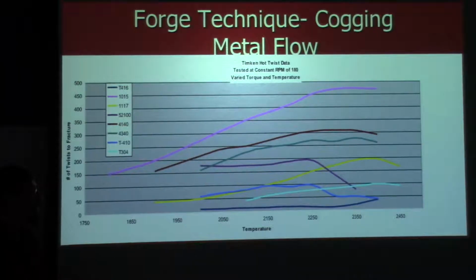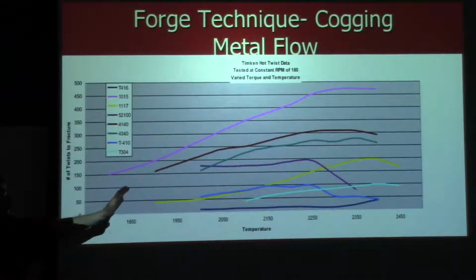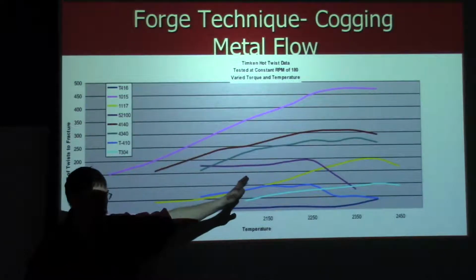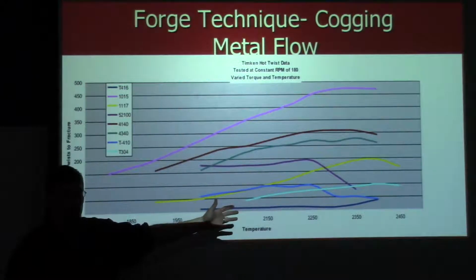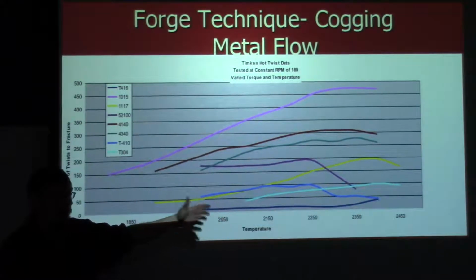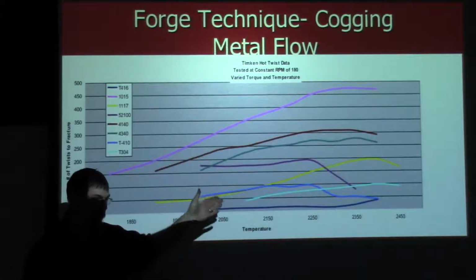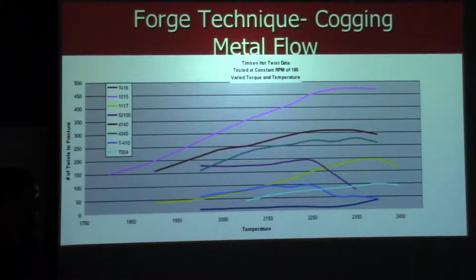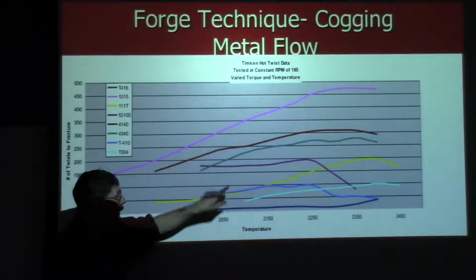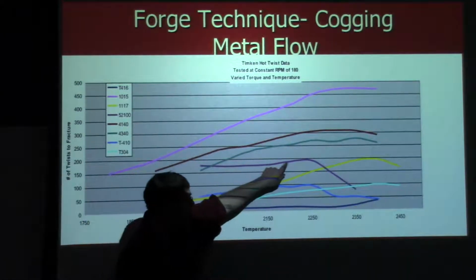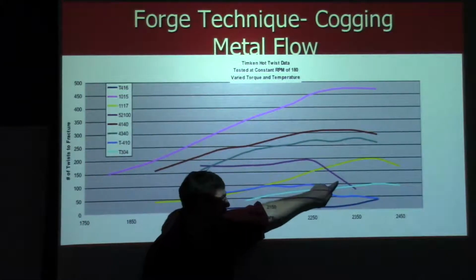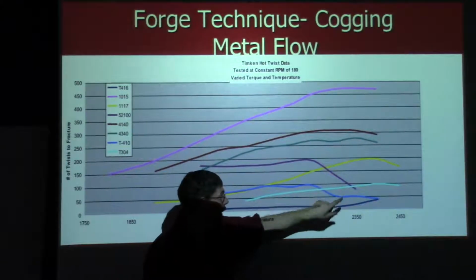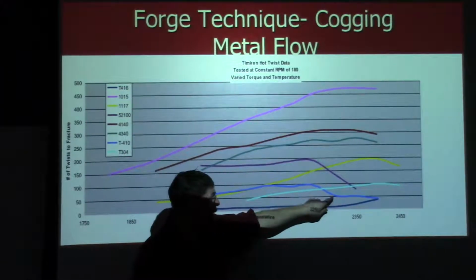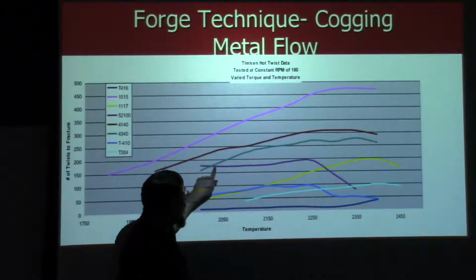So we see that in general, at higher temperature, you can do more twists before the metal is going to rupture or fail, right? So that is consistent with what we were just talking about. But I want to draw your attention to a couple of things. We have this alloy here, this dark purple. We get to this spot, and then all of a sudden, it starts to drop off. We've got one here that drops off at a little different temperature.